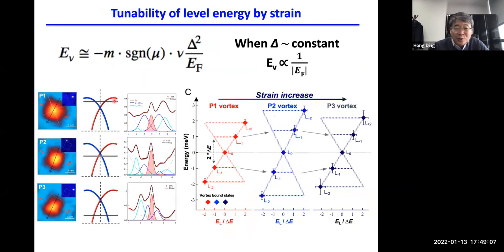We also can tune the pressure differently, so we can have a different EF, because this separation between the bound states is more or less inversely proportional to EF. Once we reduce the EF, we will see an increase of this separation. But once it crosses zero, you will see the EF decrease again, but with a negative sign, so you will see this separation decrease.